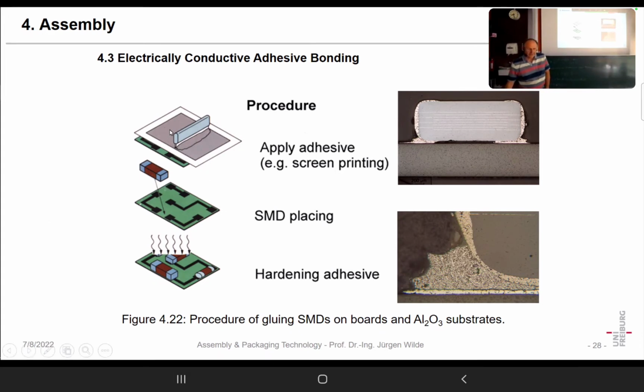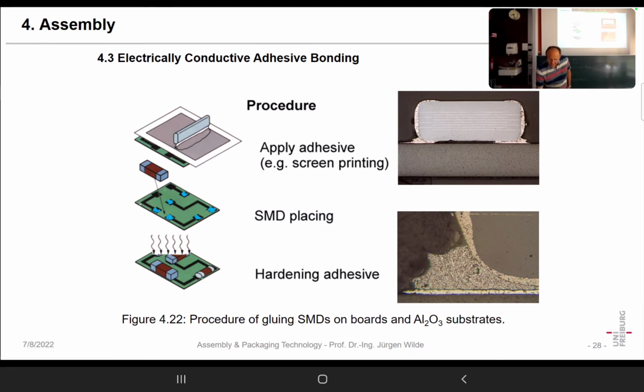We know that process already. Then we have a pattern of that adhesive on the substrate. And yes, of course, when we want to do it correctly, we only have it here on the pads. Yeah, here we have a device in a cross fashion. So here, those are capacitors. That is probably a MELF diode. And in that way, we put the device on, we place it, and then we just harden it in an oven.